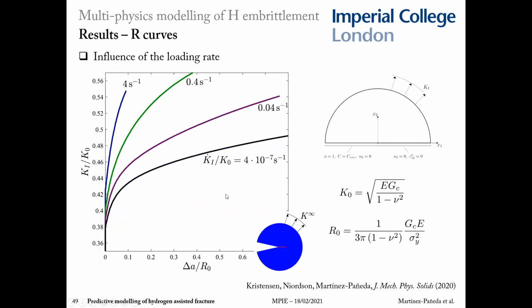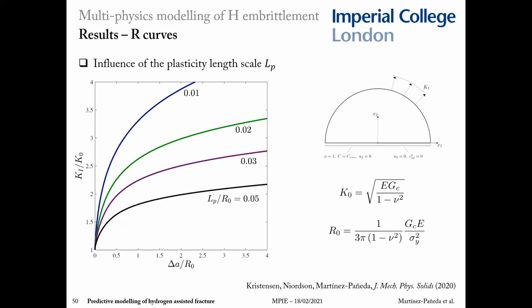What you see in this slide are the results obtained for different loading rates, showing how the model captures another well-established experimental observation. The faster the loading rate, the higher the crack growth resistance. And what I'm showing here is the effect of GNDs, one could argue, and the associated dislocation hardening mechanisms. Because we know that these strain gradients or extra dislocation gradient mechanisms will become more prominent, what we see here is that these gradient effects become more prominent when the material toughness is smaller, because the size of the fracture process zone, R naught, is smaller.